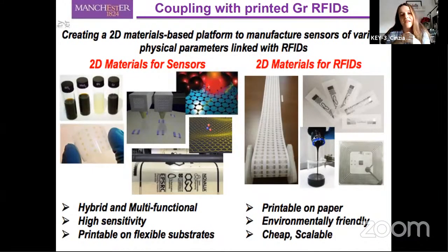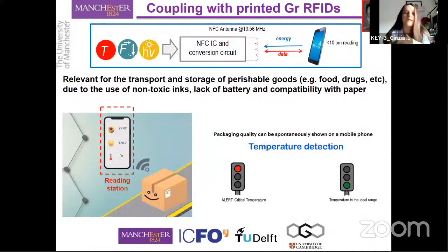Of course, the inks can also be used to make printed sensors. We have already demonstrated photodetectors, but we can also probe strain, humidity, and so on. And because they can be printed on paper, they can be combined very easily with the printed RFID. These are typically printed with silver on paper. So that means that we can basically make a wireless sensing platform completely printed on paper. And this is actually what we've been doing in collaboration with Professor Zirong Hu at the University of Manchester, who is able to screen print the graphene RFID antenna.